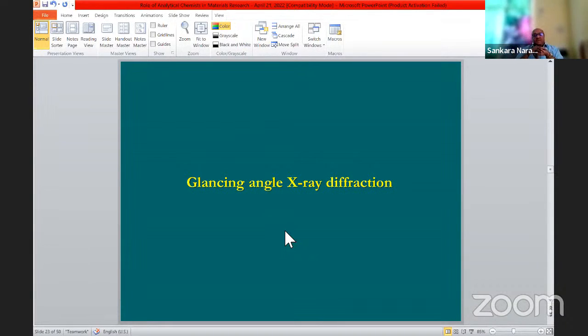It's not a problem. But if your material is a very thin film deposited on a substrate, then if you do a normal X-ray diffraction pattern, what will happen? The X-rays will penetrate through the thin film to a longer distance. So automatically your base metal peak will come very high, and the characteristic peaks of the thin film become very, very low in intensity. We may confuse whether it is noise or a characteristic peak of the particular material. In those cases, we can use glancing angle X-ray diffraction very well. So this is one example.